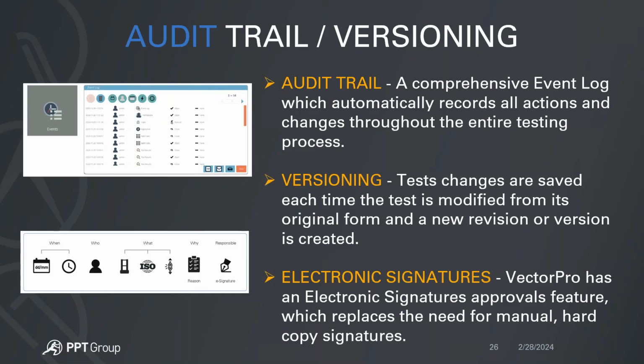So when data is actually assigned, you have a batch of data that is designated using the original speed of 10 revolutions per minute, and then you have a different set with version 2 with a batch of data that actually references the modified test using the revised speed of 5 revolutions per minute. So the versioning system is important.